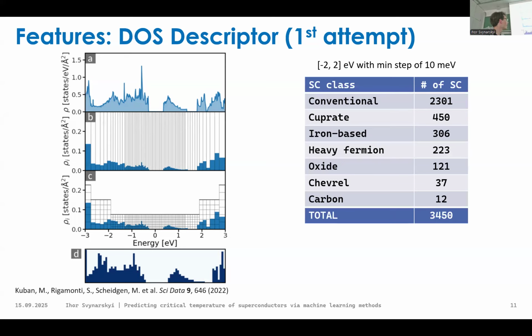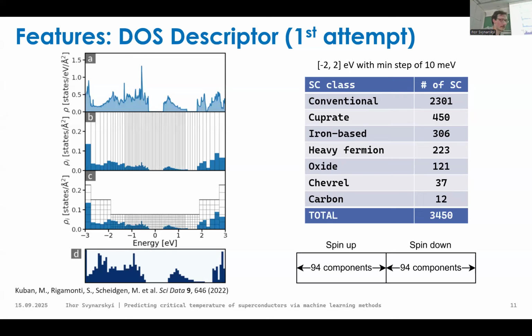So we tried to do it from minus 2 eV up to 2 eV, and 0 is the Fermi level, with a minimal step over X of 10 meV. And yes, it reduced the number of available compounds, but it provided us an ability to add descriptors for DOS with spin resolved DOS. But it was only the first attempt because we accounted only for the total DOS. So in this case, it's total DOS, without resolution of orbitals and species.